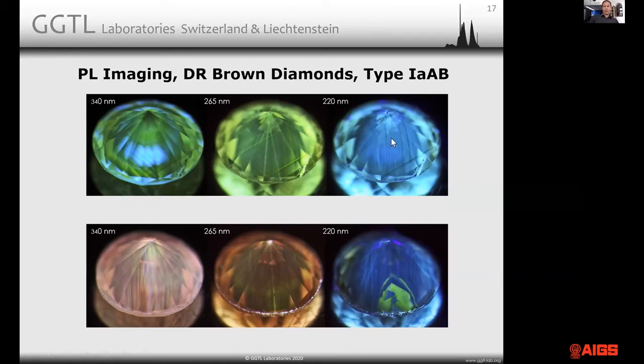These are type IaAB stones, 2 samples. You can see they're very different here. If you look at the PL spectra of these stones, they're actually quite similar, except that the ratio between the different photoluminescence peaks are very different. In the top stone, N3 and H3 plus probably the 490 nanometer band is very dominant, while down here we have seen the 715 nanometer band is very dominant.